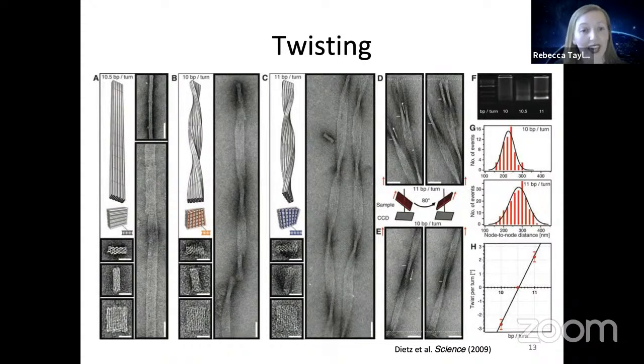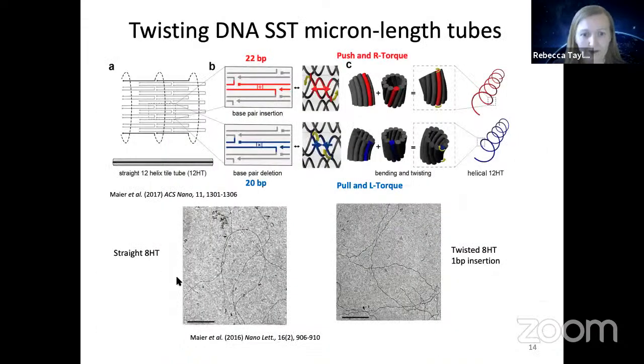And in the same paper, they showed you could independently control bending as well. So there are ways to make fixed structures that are both twisted and bent. And for people designing machines, that's incredibly useful. There have also been studies showing hollow nanotube-type structures utilizing the same principle, right? If you've got a region with sections that are too short, you can get left-handed helical structures, or you could have regions that are too long and you can get right-handed helical regions. The result shown here in these TEM images is that you can have either linear-looking, elastic filaments, and then here you've got these kinked ones, right? It looks like they've been crimped. And this is because they actually have helicity to them, right?